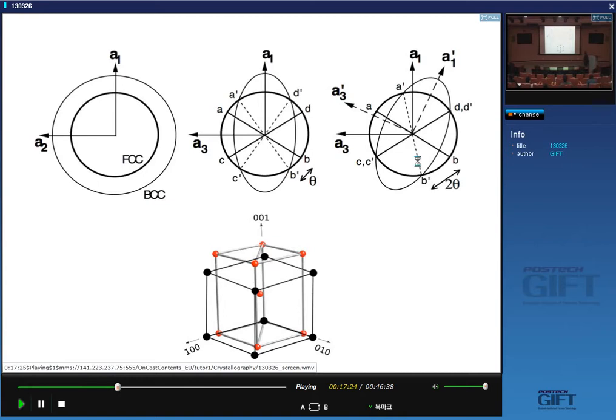That orientation relationship says that 100 of austenite in the body-centered tetragonal cell is parallel to 100 of ferrite. And if we were looking at the cubic cell, that would be a 110 direction of austenite parallel to a 100 of ferrite. So let me go back to the cubic cell.